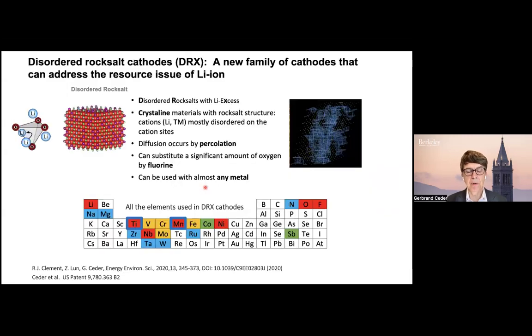At least the proof of concept worked to the point where, because we don't need a specific cation ordering, we can work with almost any metal in the periodic table. I've listed here almost all the cations and anions that have been used in disordered rock salts, and you can see almost every single transition metal has been used. Because of the partially disordered nature, you can substitute some of the oxygen by fluorine, which I'll talk less about today, but which tends to give you very good surface stability. Even if you lose 1 or 2 layers of oxygen, you get an enhancement of fluorine at the surface. That often even happens in the synthesis, so you have essentially a fluorinated cathode surface, which has extremely high stability against oxidation.